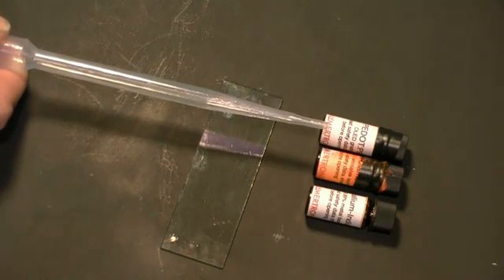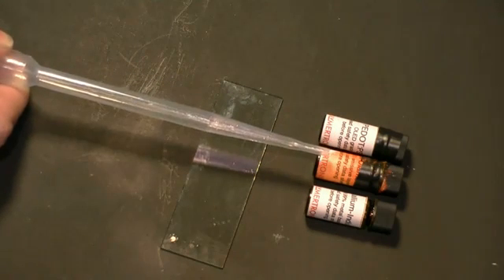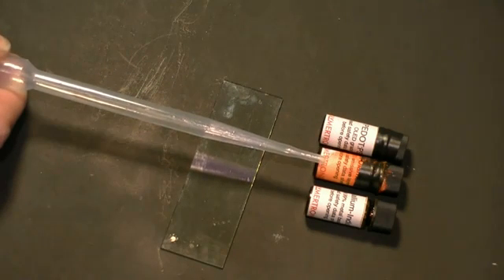These are the three components. PEDOT:PSS, it's a hole transport layer, the emissive layer, which is the red diamond ruthenium complex, and the cathode, gallium indium eutectic alloy.